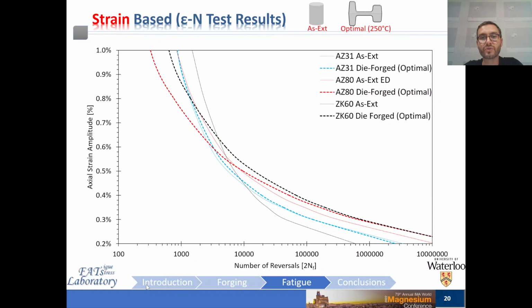The effect due to forging on ZK60 is also similar in nature. However, there's a very significant increase in ductility, which causes a dramatic improvement in the high cycle fatigue properties shown by the area denoted in green. So there's a similar transition point. However, we just have this enlarged area in green relative to AZ80, the response shown there.